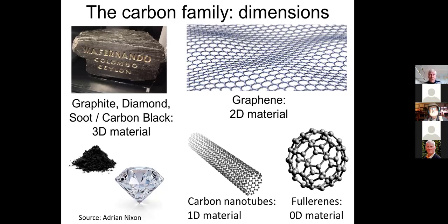On the left, you see 3D materials made of carbon: graphite, diamond, of course, everybody's favorite, soot, and carbon black. And at the top right, you see graphene, the material we're most interested in, a 2D material, which means that it is just one atom thick. That is 1/3 of a nanometer thick. It's made entirely of carbon bonded together with very strong bonds, and it yields a very high strength, and in small quantities it's been made at extraordinarily high strength.